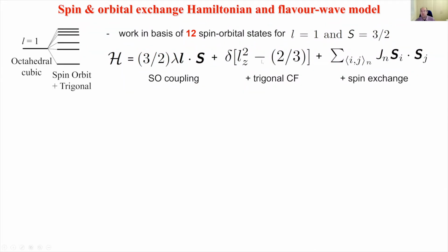So the first two terms are single-ion terms, and they give rise to the splitting of the crystal field levels. Now, if we project this Heisenberg exchange onto the level splitting induced by the first two terms, we get the XXZ Hamiltonian, because this trigonal splitting prefers the spins to be in the plane. So we need to go beyond this in order to add additional interactions that could potentially explain the gap.